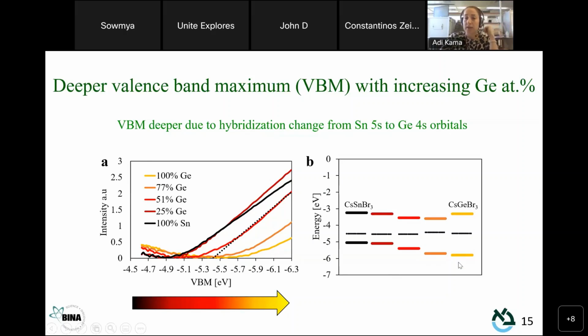We plotted here, the bottom one is the valence band with respect to the vacuum, which is 0. We calculated the conduction band from the band gaps, and we have the Fermi level from the CPD measurements using Kelvin probe.